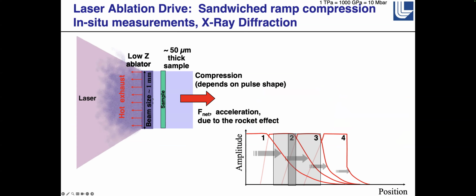We can change the intensity of the laser over time, so we can make it so that the laser starts off very low intensity and then increases in intensity. So the low pressure waves will travel first through the sample. They'll get to the sample here, and then we have a window on the other side. And as you get into the sample, you get reverberations, and so the sample is going to rise in pressure with the window and with the ablator, and essentially you can see that the pressure wave moving through your sample gradually increases the pressure within the sample.